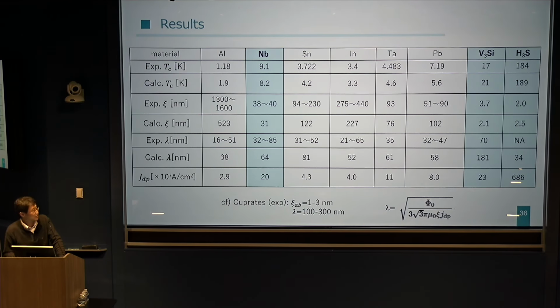We performed this calculation for a variety of elemental materials or compounds, and the blue shaded materials are type 2 superconductors. Concerning this large number, let us compare H3S with high Tc cuprates. In the case of high Tc cuprates, the coherence length is about 3 nanometers, and it is almost the same as H3S.